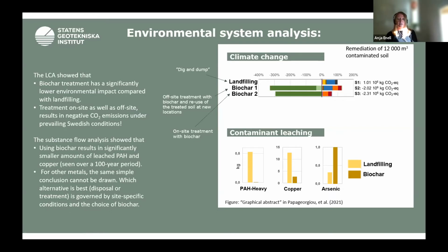In the environmental system analysis, we also did a substance flow analysis, and this is what you see here below. And we used the results from the field trial here, and then we simulated leaching over 100 years. And as you can see, we have a reduction in concentration of PAHs when we compare the landfilling options with the treatment with biochar. The same for copper, but for contaminants that could act as anions in soil, like arsenic, chromium, molybdenum, vanadium, there could even be an increase when you use biochar. And this is probably because some biochars could increase the pH in the soil. And that increased pH can make those compounds more mobile.